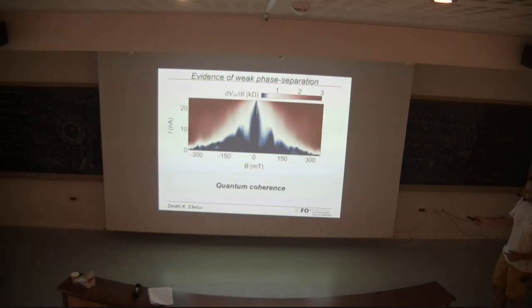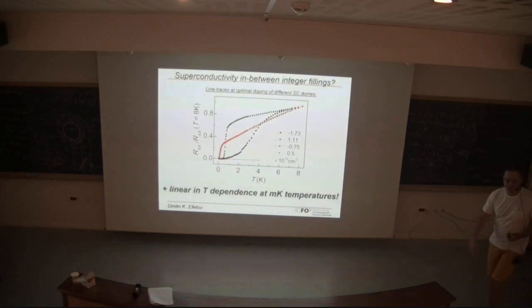But also to answer your question, this is for example temperature-dependent data taken for every superconducting pocket. So for example, this temperature-dependent data here, the red and yellow lines, these are from the states between 0 and 1, and 0 and -1. So these are the newly observed superconducting pockets. And as you can see, the temperature dependence leading to superconductivity is very linear, down to temperatures of about 100 millikelvin. And even if we lift the superconductivity in the magnetic field, the temperature dependence in weak fields still continues to be linear there.